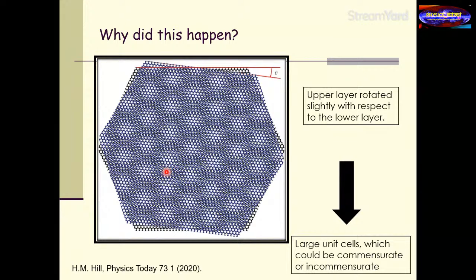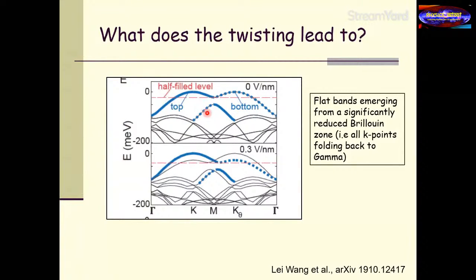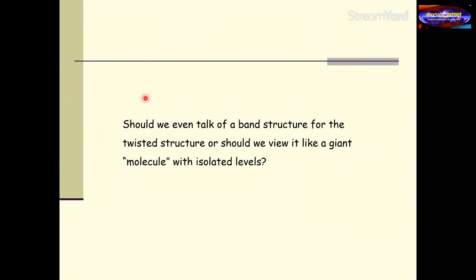molecules. And that's the reason why, when it comes to the bulk solids, what they said was, we have to expect that what is happening is you have a big giant molecule. You're not talking about bands, you're talking about isolated levels which are emerging in these solids. That's the reason why people said that there is no band structure to talk about. What they thought was that essentially we are talking about almost flat, dispersionless bands emerging, and that's the reason why we need to consider strong electron-electron interactions to talk about these systems. So the basic idea that persisted at this point was that these twisted bilayers or twisted layers of van der Waals heterostructures should be viewed as a giant molecule with isolated levels. Okay, so far so good.